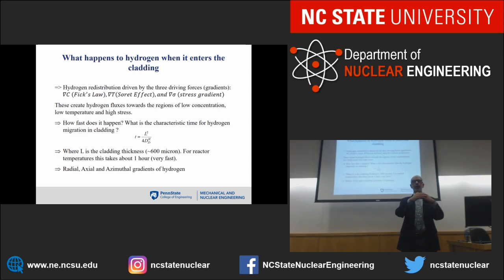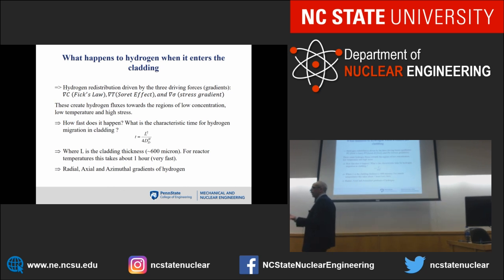Let's say that the hydrogen is in here and it's all homogeneous. It's never homogeneous because I have a heat flux, so the temperature inside is higher than the temperature outside. But let's say that it was homogeneous. Now my oxide spalls off, so suddenly this is cold. So then the hydrogen will now migrate in. And I'm saying that the response time would be very small, about an hour, which means that it would be much smaller than the normal exposure times that you have in the reactor, which is days or months. So for all intents and purposes, we are more or less at quasi-equilibrium all the time.